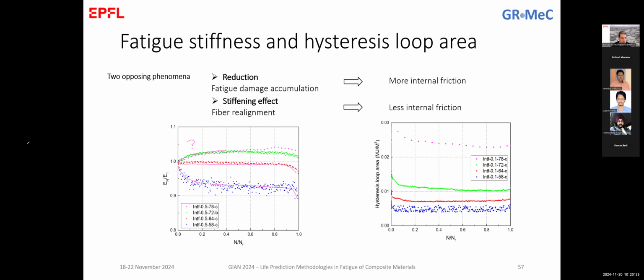And then we also compare the self-generated heating, which is quantified, if you like, with the area of these hysteresis loops. And again, here we had similar performance as with the stiffness. The heating was, as expected, lower at lower stress levels, and it was increasing as the stress level was increasing.